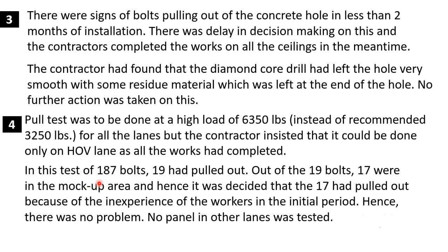So the tests were conducted. In this test of 187 bolts, 19 had pulled out. Out of the 19 bolts, 17 were in the mock-up area and hence it was decided that the 17 had pulled out because of the inexperience of the workers in the initial period. Hence, it was decided that there was no problem. No panel in other lanes was tested. So this tunnel contained at least 3 different lanes: the HOV lane, then the east and westbound lanes. So this test was not conducted in any other lanes.